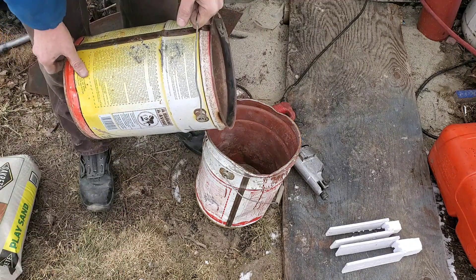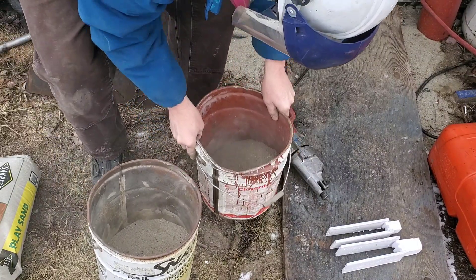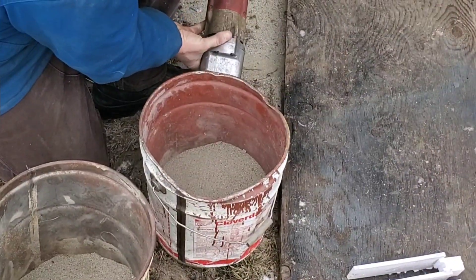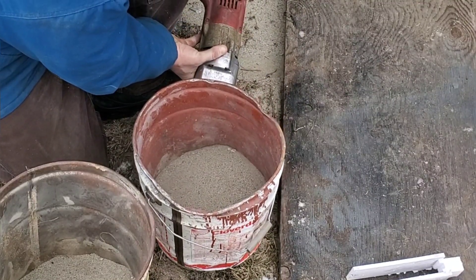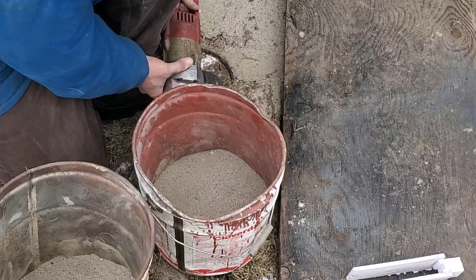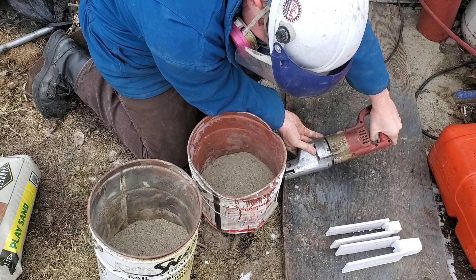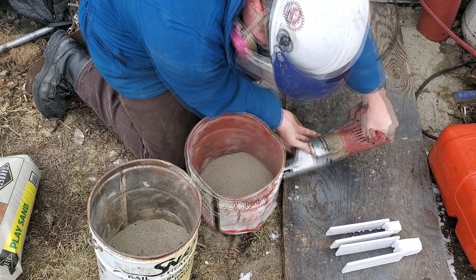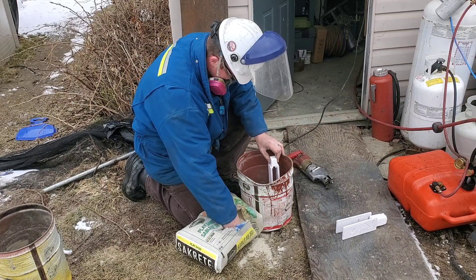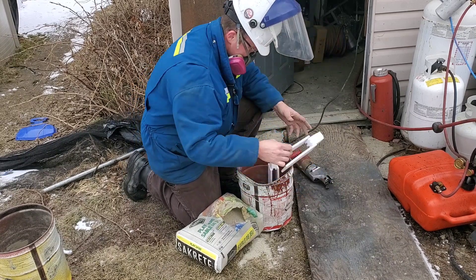Today's advancement in learning came from Kelly — the guru, so to speak — and he suggested that it was a matter of filling it in stages to keep everything straight. So firstly I'll put the base in, compact it, then put another light coating of sand on the bottom, and then place in the parts and compact it in steps as I go up. This does in fact create quite a bit less distortion in the parts.